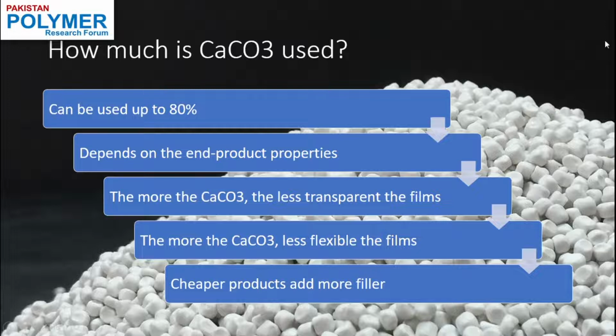But for end products that are to be used in very low-grade applications such as making a garbage bag or something like that, you can easily use up to 80% calcium carbonate to make a low-quality master batch that can be used fairly well in your application while reducing the cost at the same time. However, when you are striving to achieve films which are more flexible and more transparent, you have to reduce the amount of calcium carbonate that you're using.